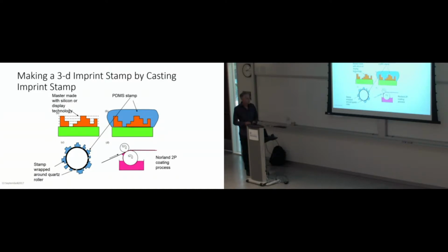But you can also put it on a plate or all kinds of different things. But we wrapped it around a quartz cylinder. And then we had a roll-to-roll, which we had a Norland 2P, which is a UV curing polymer. And we very precisely control the thickness. Using these optical Filmetrics, we could control to fractions of 0.05 micron liquid levels.